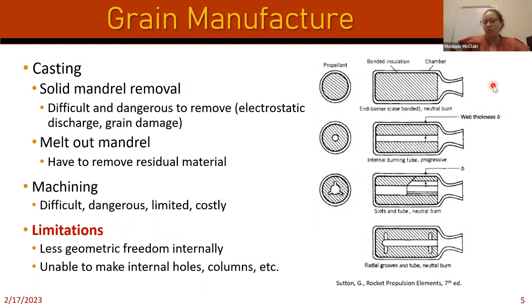However, if you want to change that thrust profile from something like an end burner, you would need different kinds of internal geometries. The way we can make this geometry is by having some mandrel in the center here and then pouring that slurry around it, letting it cure, and then we remove that mandrel later to get this internal geometry. Based off of that, we have several options. We could have a very simple circle here. If we burn this, we would ignite in the center, and then this burning surface area would increase over time, which would change how it burns, or the thrust profile. We could do fancier types of mandrels, with fins or some weird grooves. But as you can imagine, the more complicated this mandrel design is, the more challenging it's going to be to remove. And it's really important that when we design these propellants, that removal has to be done in a safe manner.